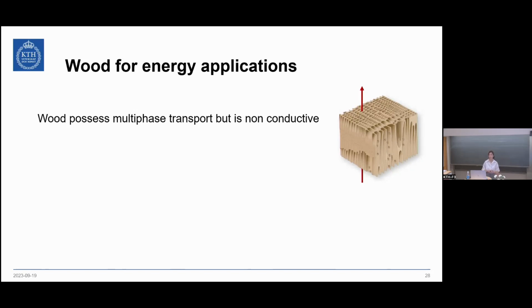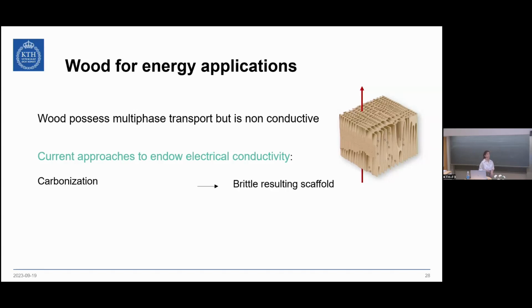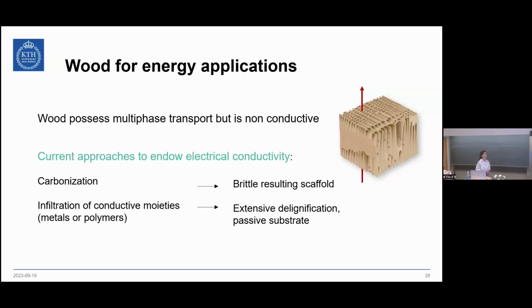However, as you're probably familiar, wood is electrically non-conductive. So to impart electrical conductivity, what has been done in literature focuses mostly on carbonization. However, in this case, what is obtained is a very brittle scaffold. Otherwise, if the structure wants to be preserved better, then the possibility is to infiltrate conducting moieties. Most of the cases are either metal, metal oxides, as well as conducting polymers. However, in this case, again, extensive delignification to open up the structure is necessary, which means that the wood is just used as a passive substrate to hold the polymer or the metal, but is not actively participating in the